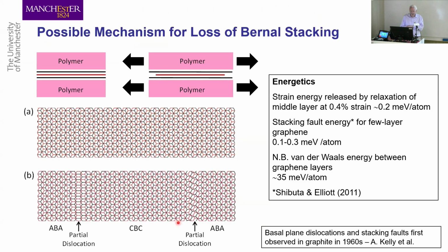And what it means is that for this 3-layer material, the B layer in the middle doesn't follow the A layers. So you can see this is the polymer sandwich. You've got the graphene sitting there. And what happens is that there's a very low shear stress, very low stacking fault energy, and it's very easy for the middle layer not to keep up with the outer layers. And so you get this situation of partial dislocations and these stacking faults. And we see it in the Raman spectrum.